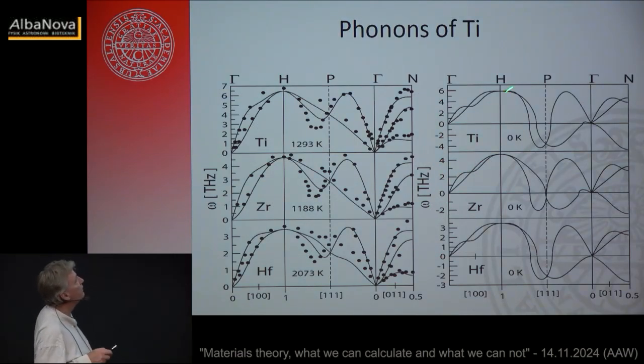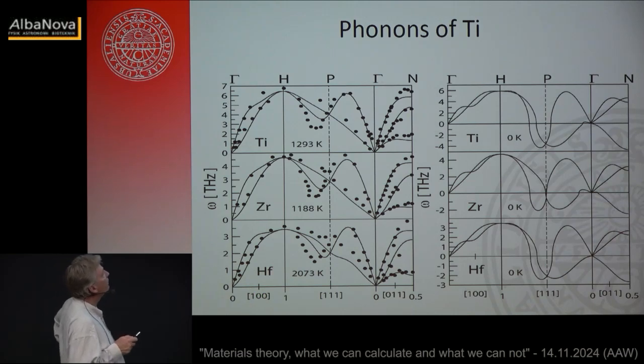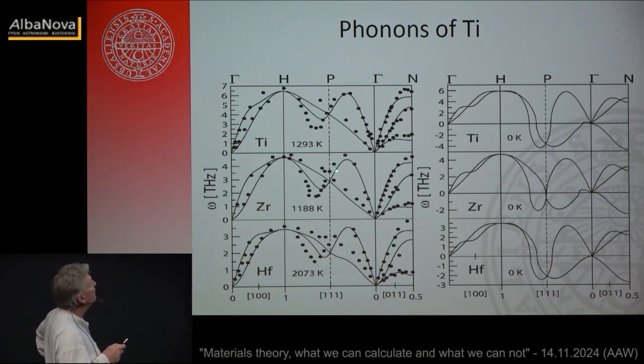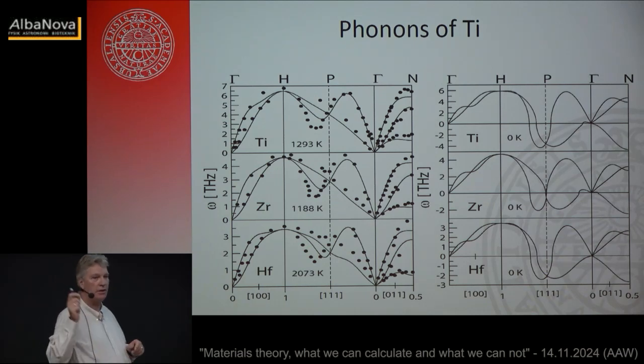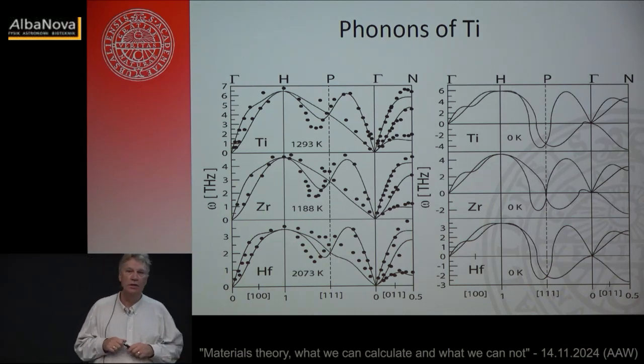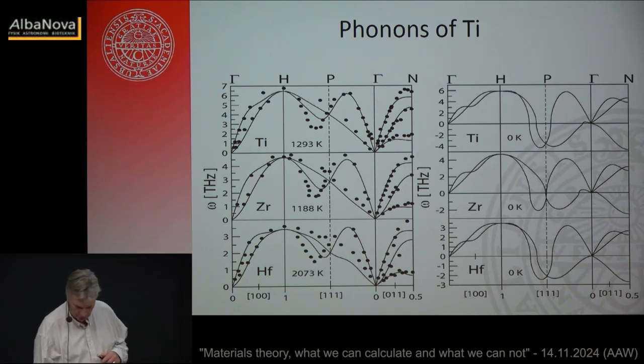So now we go from the failed static lattice here to the dynamic lattice over here. And here all of a sudden the measurements, the black dots, are in pretty good agreement with the theory, which is the solid line. So all of a sudden, all these imaginary modes are gone. We can reproduce much of the measurements. We fail a little bit. This dip here, for instance, is not as steep as it should be for zirconium, but no theory is perfect. And so we were actually kind of happy with this. So I would say check on that also. That's also something we can do, lattice dynamics and phonons.